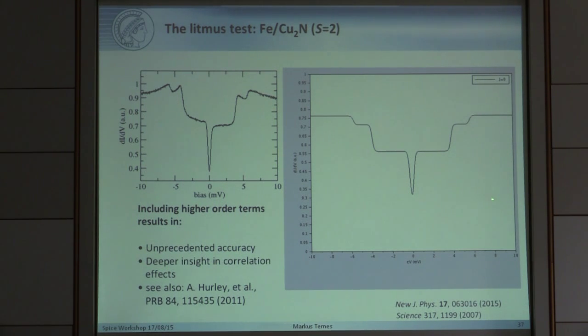That is anisotropy included, second order. And now you just increase J, the coupling to the substrate. And you see, wow, OK, I get my peaks. Next, you increase also the U, and you see you get actually almost a perfect fit. That is what you can do. So you can get parameters out of your data.